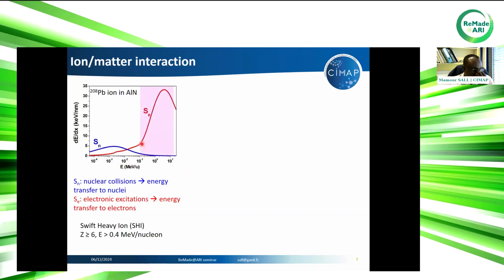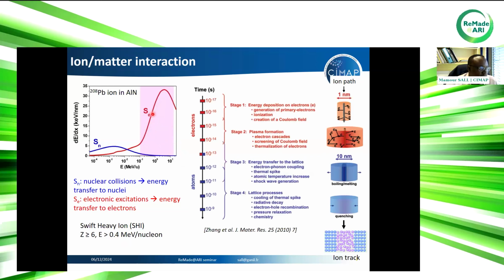So as I said before, we would like to use ionizing radiation. This means we need to be in this range of energy loss, high energy loss. So for this, we will use what we call swift heavy ion. According to GANIL, swift heavy ions are ions from carbon with energy above 0.4 MeV per nucleon, but this is very subjective. But the point is, with swift heavy ions, we should be in this region of energy loss with very high electron stopping power.